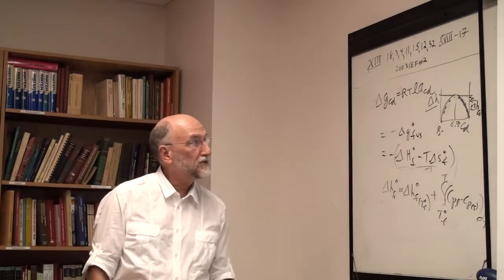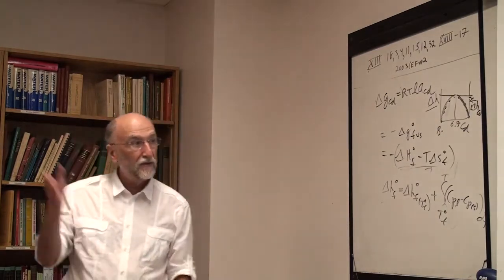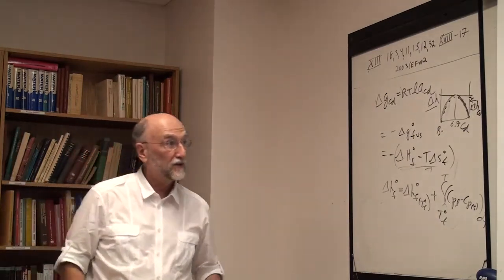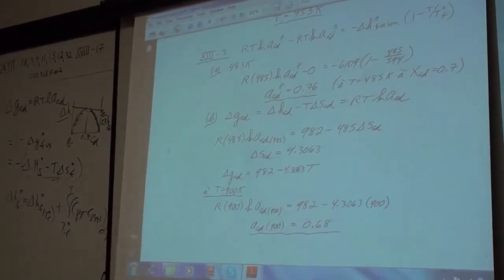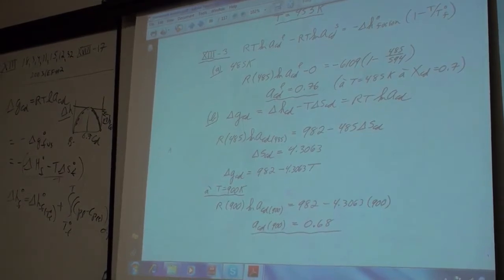Okay, but the point here is that just measuring the liquidus gives you the activity along the liquidus. It gives you the partial Gibbs energy, or delta mu, which is the same thing, along the liquidus, but it does not give you the value of the activity at any other temperature. For that, you need additional information.